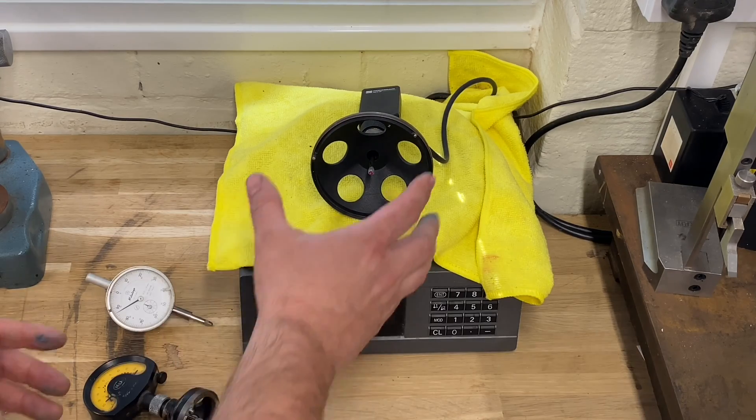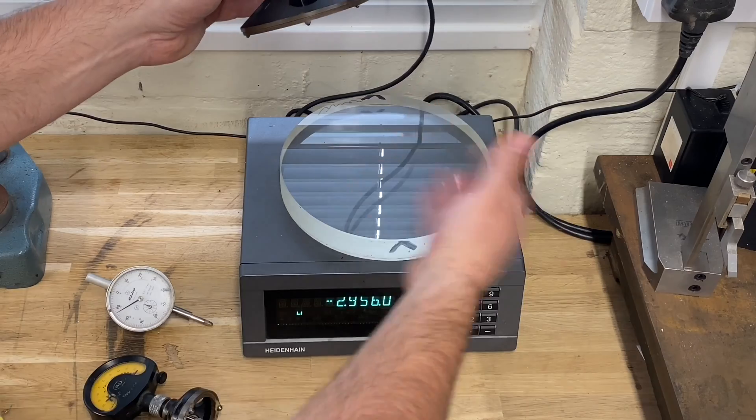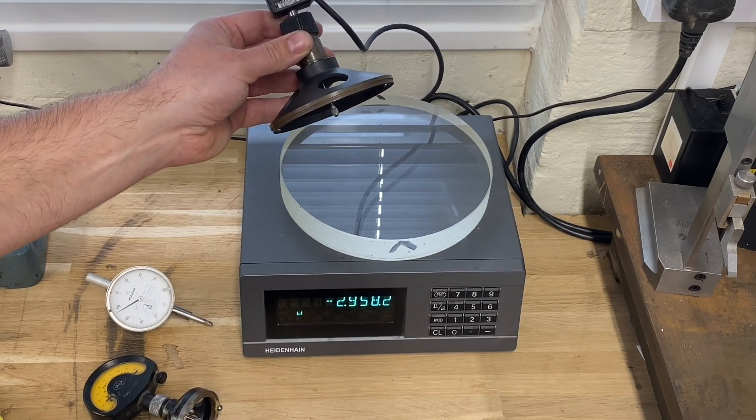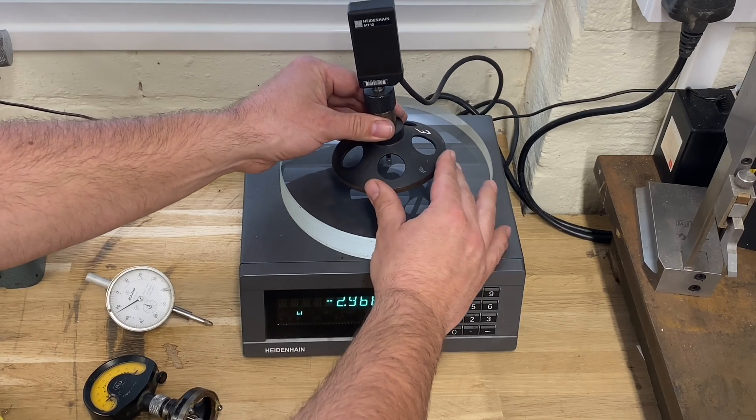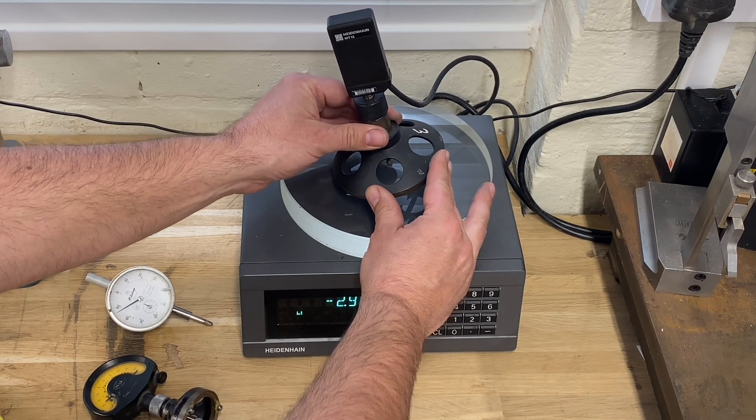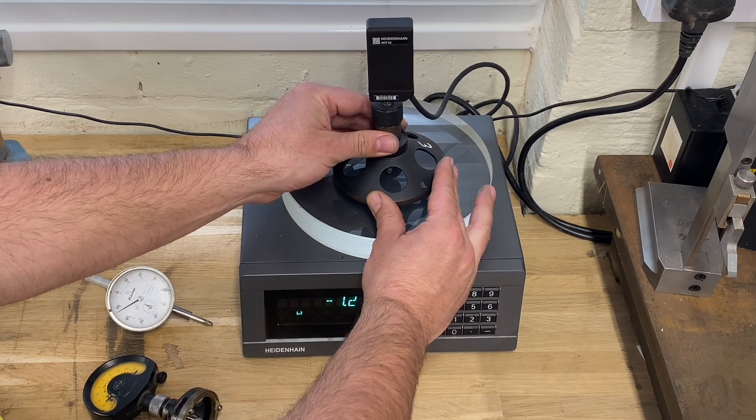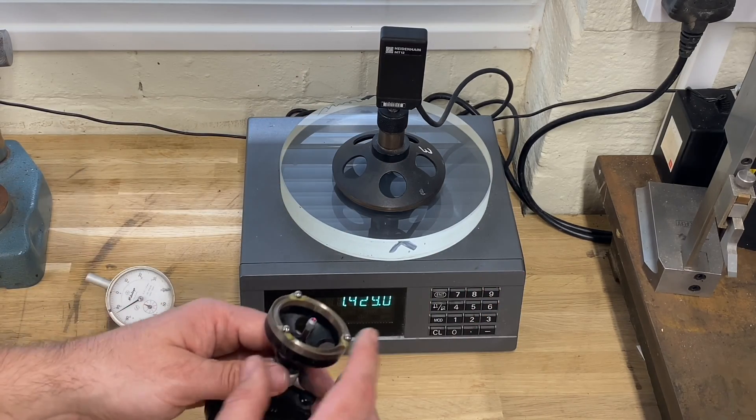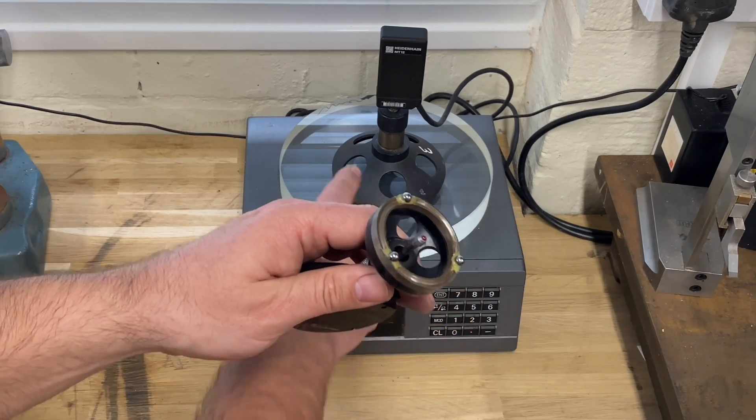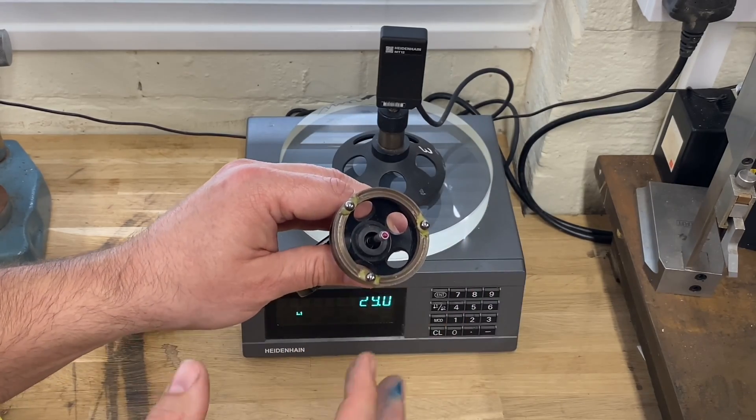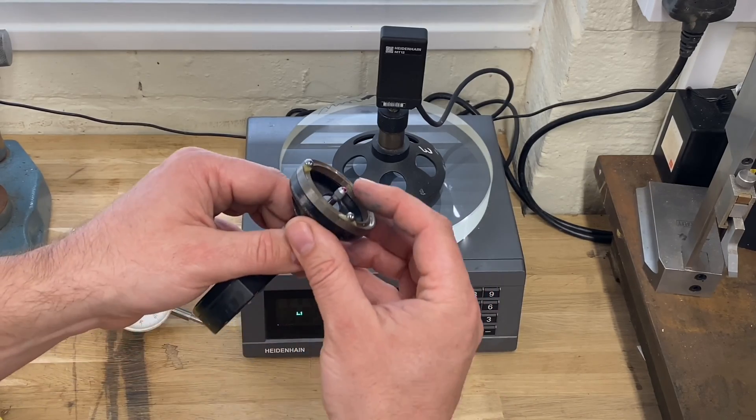The way this particular gauge is calibrated is the same sort of way. Under this cloth I've got a precision flat. This is about 200 millimeters in diameter, made from fused silica, and it's very flat, about half a micron flatness across the whole thing. The way I would calibrate this spherometer is I'd carefully place it down on two balls, then down onto the probe contacts next, and then lastly the third ball contacts. What we've achieved is we've defined a plane between these three balls. Three points define a plane, and we've defined that plane now. The probe is now aligned with that plane.